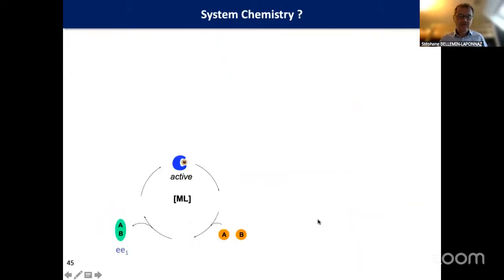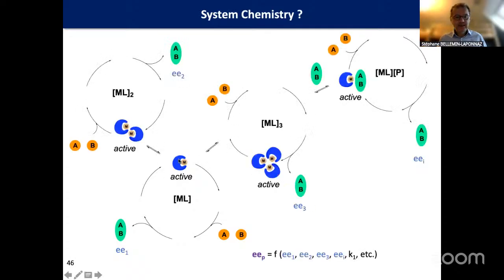But this is true if you have a very simple and single active species. But in reality, what you have seen here is that the active species can make dimers. The active species can also make trimers. We have seen that the active species can react with the product to give a new active species, which means that the selectivity of the reaction is the result of competitions between different active species, and all give a different selectivity, which means that at the end, it makes it even more complicated.